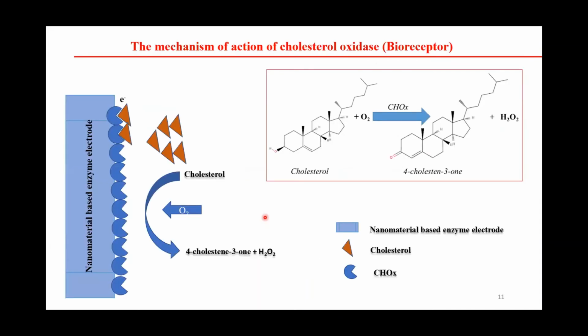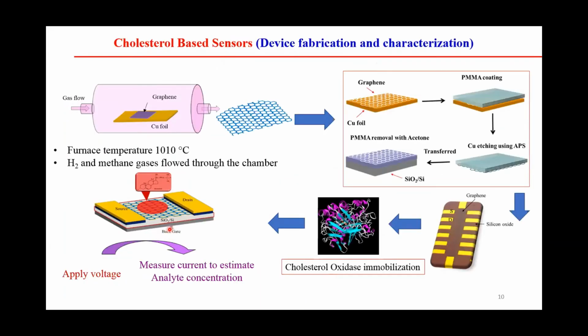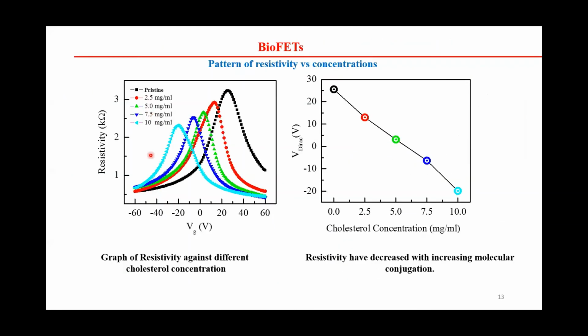If you look in more detail, you can see this is a back gate. We apply the voltage on the bottom side, with a fixed voltage and a fixed current. But when we increase the back gate voltage, the charge carrier concentration changes, from minus 60 volts to plus 60 volts. There is a charge neutrality point, where the carrier concentration varies as the gate voltage varies. At one point we see the transition, and that point is known as the Dirac point, or the charge neutrality point.